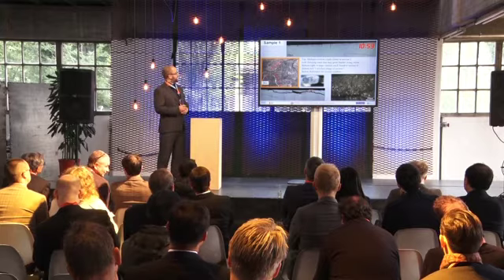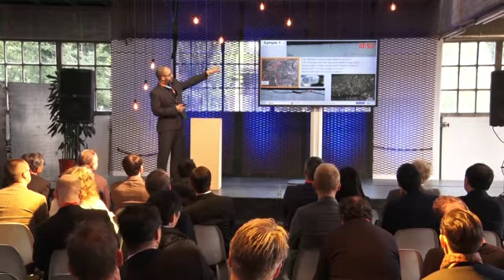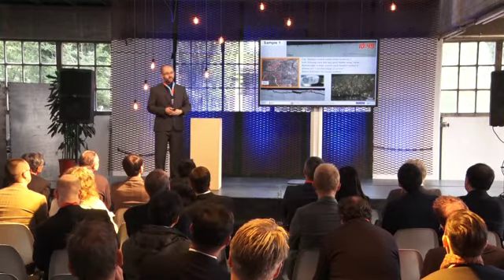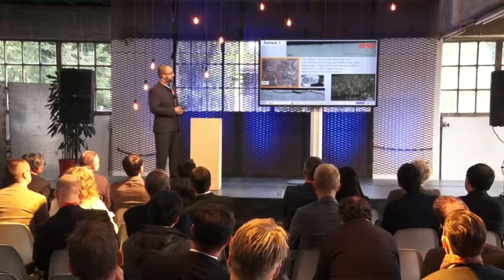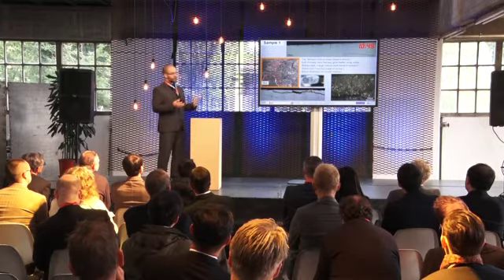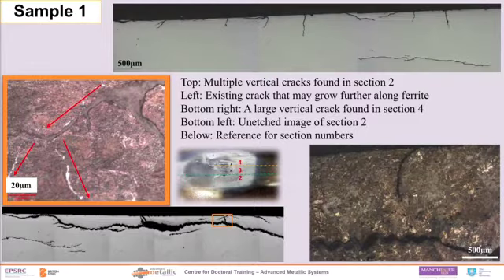Okay, so looking at the running band a little bit more, I see from the top image you've got quite a lot of vertical cracks, so this is because of large thermal input. It's the sudden cooling due to the massive heat sink of the rail that then causes large tensile stresses that cause these vertical cracks to appear.